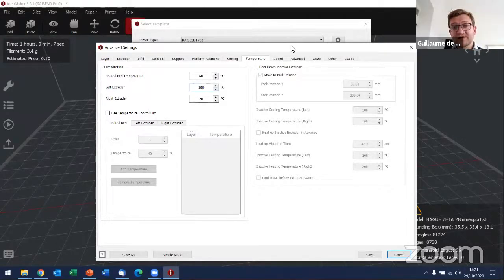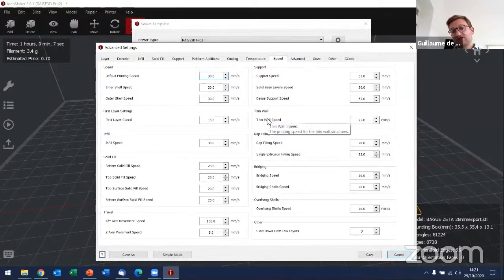And the last one, obviously, is printing speed. This is really of importance. If you try to print really too fast, you may have a few problems of filament breakage, nozzle clogging, or just imprecision in the part. And of course, if you go too slow, you're going to end up with a part that takes ages to be printed. So you need to find the right balance. Usually, something in the range of 20 to 30 millimeters per second is the correct value for our materials.